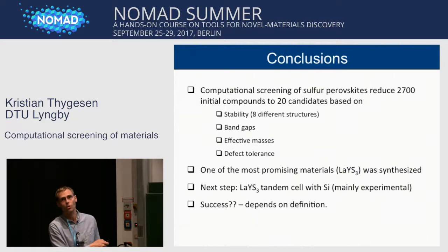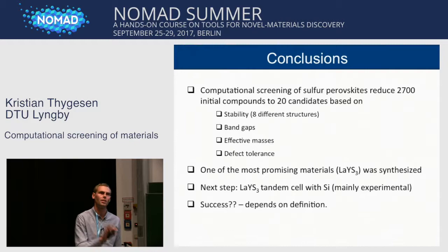The lanthanum yttrium sulfide has been successfully synthesized, and what the experimentalists are doing now is looking at integrating this material with the silicon low band gap photoabsorber, with the aim of using that as a tandem solar cell, or perhaps even for 2-photon water splitting. So, is this a success? Well, I think that just the fact that the experimentalists managed to make this material and confirm our theoretical prediction can be viewed as a success. Whether it's a real success, I think depends on whether this will eventually make it into a device that can do photovoltaics or hydrogen production at high efficiency. And this is still to be answered.